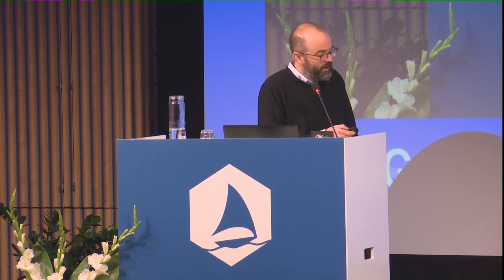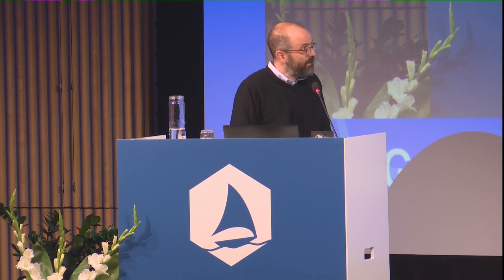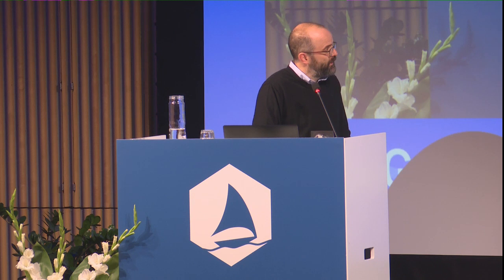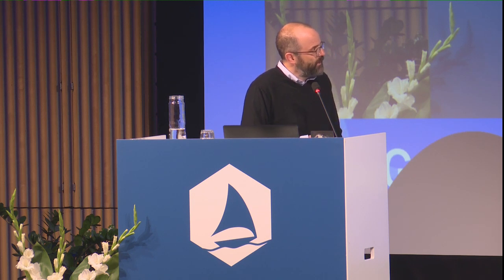So by doing that, Pablo Jarillo-Herrero at MIT reported the remarkable discovery last year that, in fact, if you twist these systems to the magic angle, really spectacular physics emerges. In particular, they identified superconductivity, also the emergence of a Mott gap at half filling of that low energy flat band. The basic model that they apply is that in this magic angle configuration, again, you have this moiré lattice, and the electrons basically condense on the AA sites of this moiré lattice. That results in something that looks like a Hubbard model.